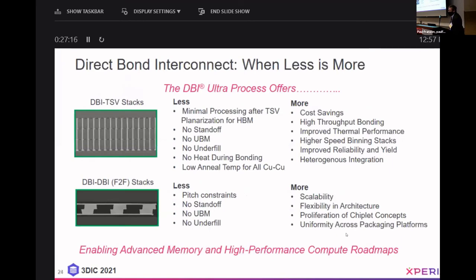Just a final slide here. Direct bond interconnect, where less is more. This DBI Ultra process offers for DBI TSV stacks minimal processing after TSV planarization for high bandwidth memory, no standoff, no underbump metallization, no underfill, no heat needed during the bonding, and just a low anneal temperature after to anneal the copper to copper bonding. More cost savings, higher throughput bonding, improved thermal performance, higher speed stacks, and improved reliability and yield. And then also, as we saw earlier today, possibility of heterogeneous integration.